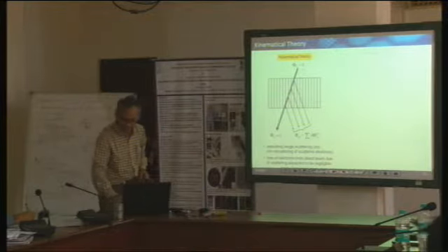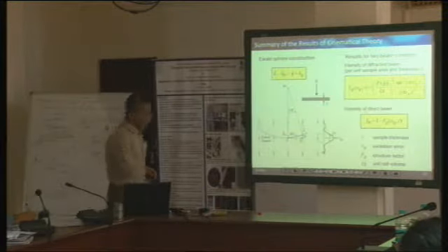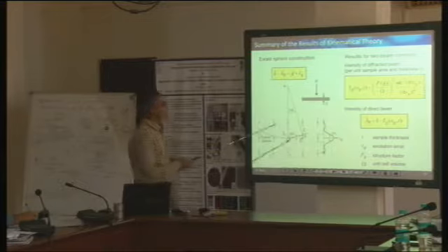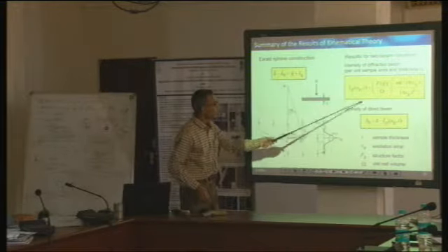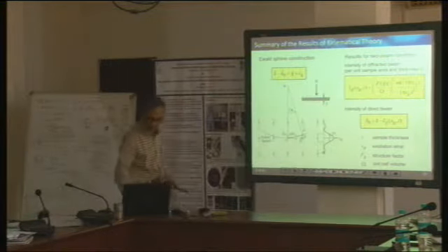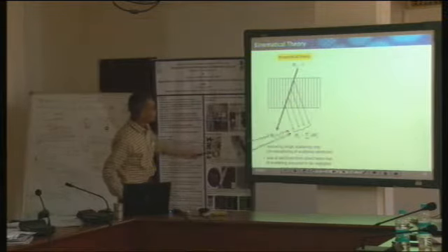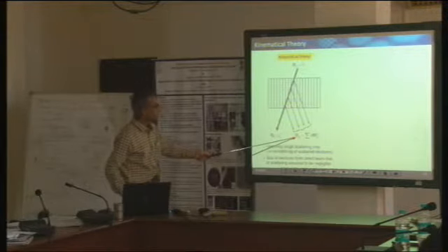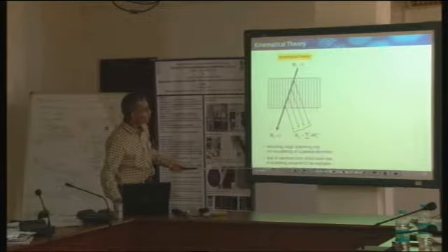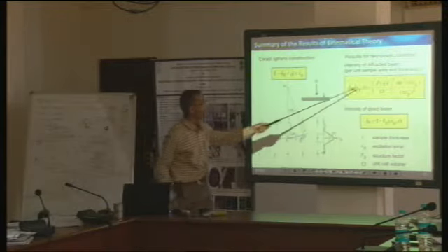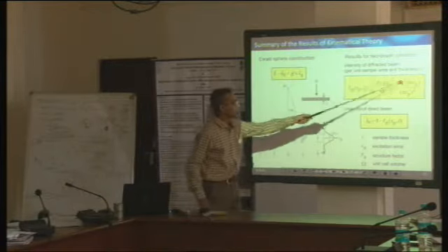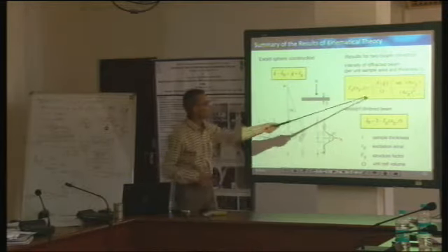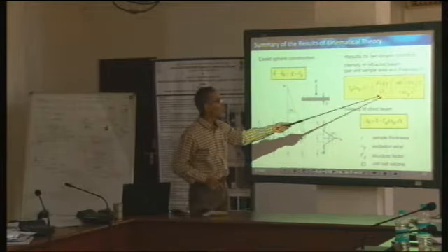Under these conditions, it is possible to derive a formula for the scattered intensity. This is the magnitude, and the square of that would be the intensity, and the formula for that intensity is this one. Here F is the structure factor, this must be the volume of the unit cell, and so on.